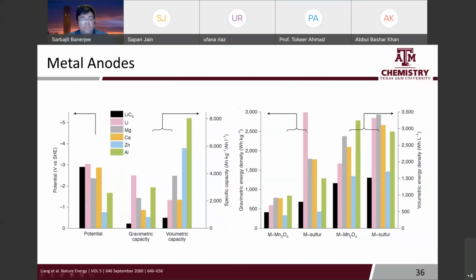So here's an article from Liang and Yan Yao's group, where they have looked at the potential of different electrodes, lithium, magnesium, calcium, zinc, and as you can see, this is compared with graphite. So using lithium metal gives you a little bit more of a potential. Magnesium will give you, and this is why magnesium has lower potential, straight out of your general chemistry electrochemical series, right? Calcium gives you a little bit more. Zinc, of course, gives you a lot less.